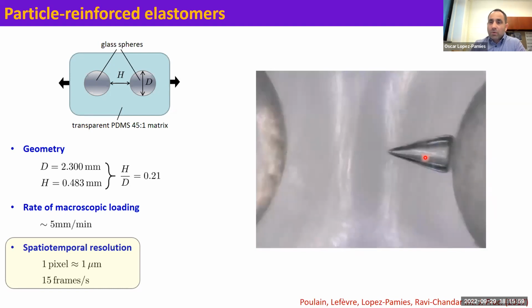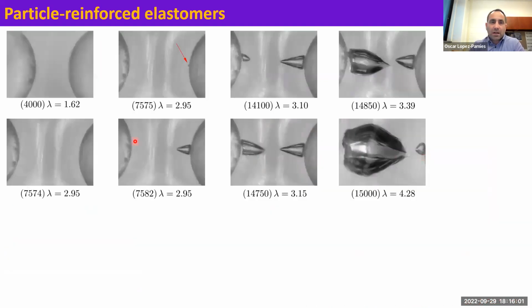And then what happens when you remove the forces is this. These are still pictures of that movie. Essentially, you have nucleation, propagation, secondary nucleation. Then this secondary nucleation of a crack takes over, and this one goes away.